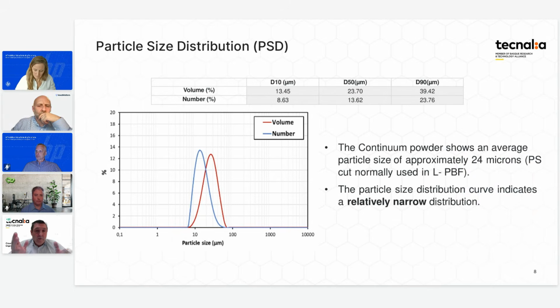As I said before, we have quite a monomodal distribution, also very narrow, with D50 around 23 microns. Just to give an idea, the typical binder jetting powders are below this 20-25 microns. So, as I was saying before, this is slightly coarser, but it's still good enough for the sintering process. And that's going to have a good impact on the flowing property compared to finer powders. So that's a good combination, a good compromise for the process.